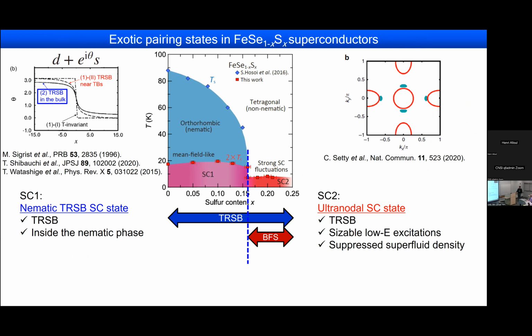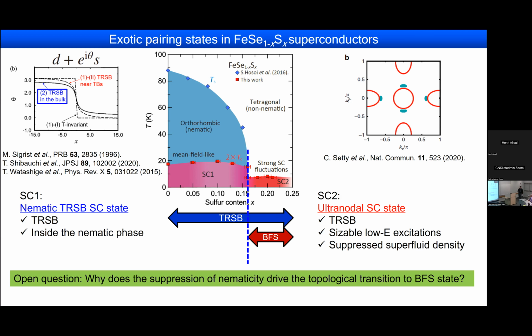Okay, so let me summarize my talk, saying that we have evidence for time reversal symmetry breaking throughout SC1 and SC2, but we have evidence for Bogoliubov Fermi surface only for the SC2 region. So there is some kind of topological transition to go from SC1 to SC2, and SC1 is a nematic time reversal symmetry breaking superconducting state, and SC2 is the ultranodal superconducting state with the Bogoliubov Fermi surface. But here is an open question. Why does the suppression of nematicity drive the topological transition to this Bogoliubov Fermi surface state?